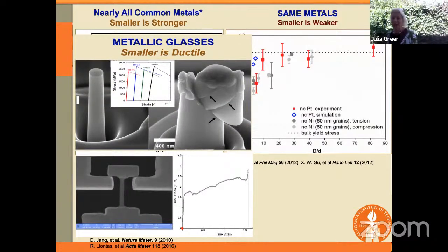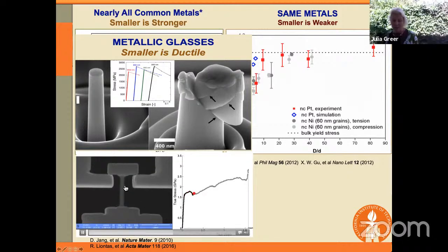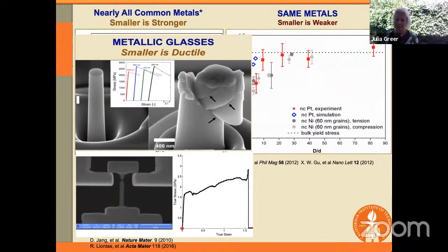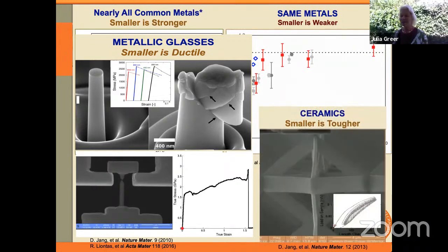For example, if you look at glass, we know glass to be very shatterable, but at the nanoscale, if you look at the tension of this single glass nanorod whose dimension is 150 nanometers, watch in this region, right in here, you can very clearly see it forming a neck. Now, of course, we know that this behavior is much more typical of metals as opposed to glasses. This glass thinks that it's a metal, and you can see that it's deformed over 100% before failure, which is very unusual for glass.